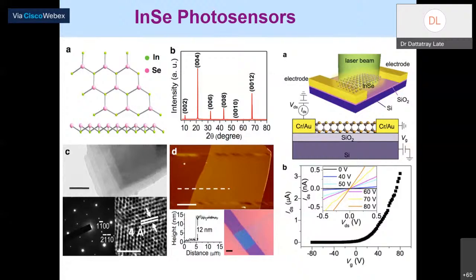The only issue is characterization: how will we characterize 3 layer, 2 layer, 1 layer, because the spectra for 1 layer, 2 layer, 3 layer is similar in nature, right? So we use a lot of transmission electron microscopy and AFM measurement to distinguish 1 layer, 2 layer, 3 layer, of course 4 layer, 5 layer. I can do Raman spectroscopy and characterize the material. Of course, this gives very good mobility based on this device.